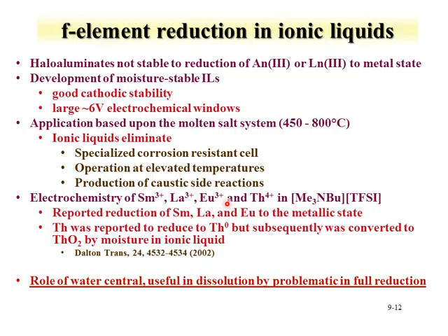There is some data in the literature on the electrochemistry of lanthanides and thorium in an ionic liquid, one that we're interested in investigating. In this system, the lanthanides have been reported to be reduced to the metallic state, and thorium was surmised to be reduced to the metallic state, but was oxidized by moisture in the liquid, and the journal is shown here. This work does point out an important consideration, that the role of water is a central component in the chemistry of ionic liquids.